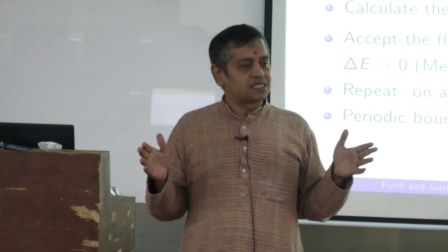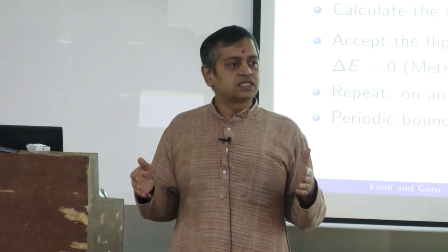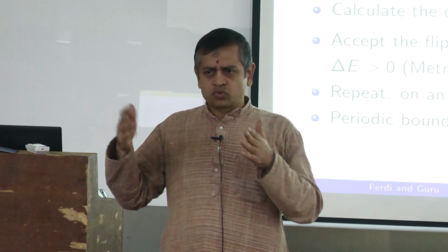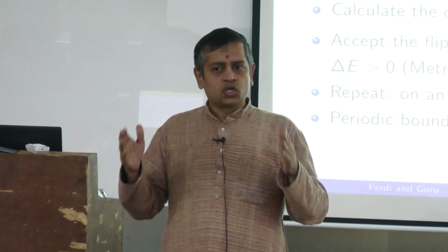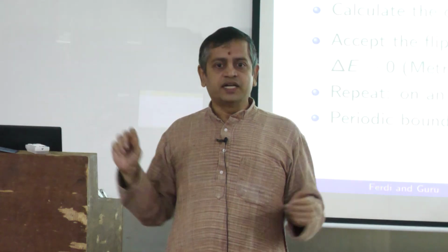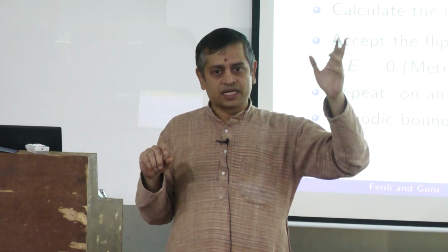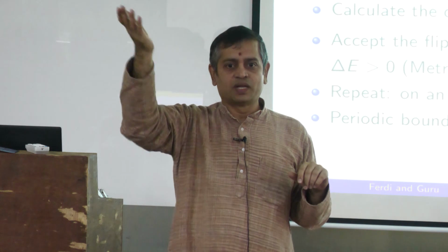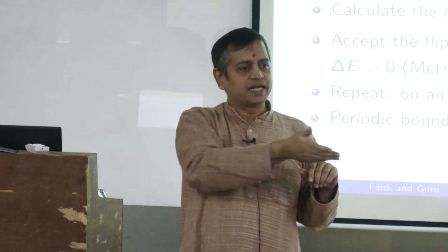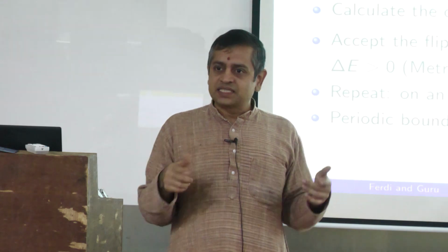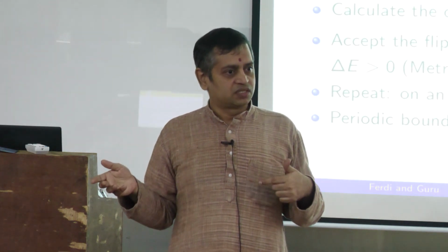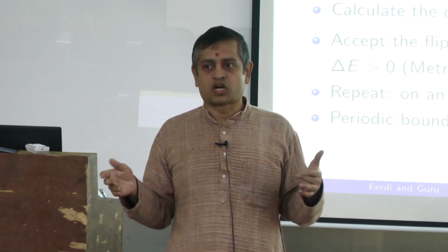So, in typical simulations done in Monte Carlo, there is something called finite size effect, and to learn what it is or how much it is, you do it for different sizes and you plot the property that you are interested in as 1 by size, and then you will have data points, you can extrapolate the data to 0. 1 by s equal to 0 is equivalent to s equal to infinity. So, you can say that this is what an infinite system would probably have. No guarantee, but this is a process.